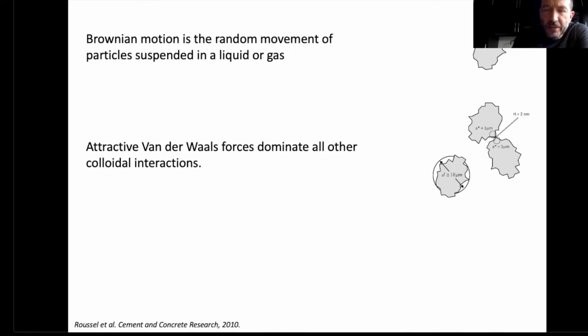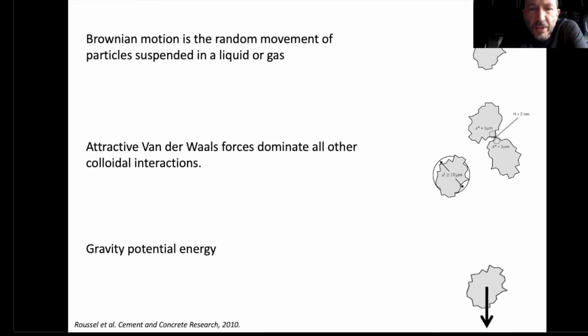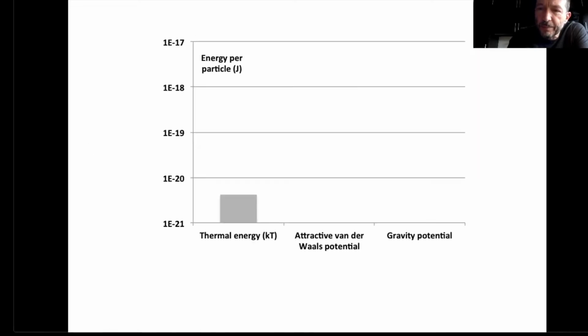And we have as well, of course, as already discussed, some gravity potential energy that could induce a sedimentation of the cement grains. It is possible to get an idea of the magnitude of these various energies or potentials and to compare them. That's what we do here. So, as already stated, I take as a reference the thermal energy, kT, k being the Boltzmann constant and T the temperature in Kelvin, and I compare that to the two other potentials or energies in the system.